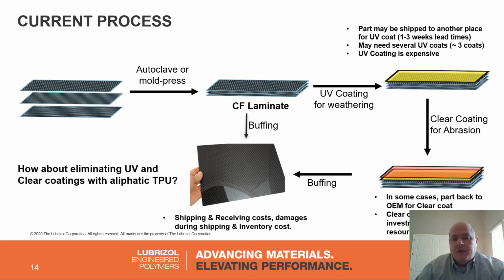In the case with TPU film, we can remove the UV coating step and the clear coating for abrasion step. So when you had seen those ladies putting the carbon fiber down inside of the tool, instead of putting the carbon fiber face down on the tool, you'd put a TPU film first and then the carbon fiber behind it. When that goes through the curing process, the TPU film will laminate directly onto the carbon fiber, giving it the scratch resistance, the coating, the UV protection.